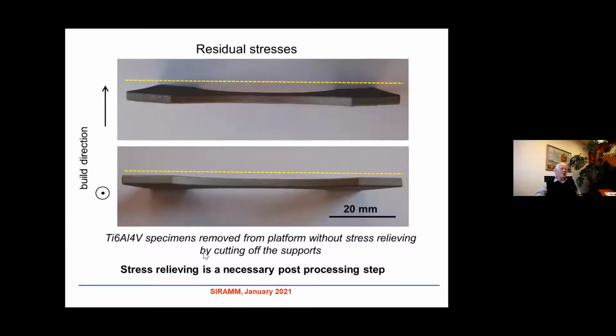Here I would like to show you specimens which we prepared for our testing of Ti6Al4V. The build direction in the first case, on the top, was in this direction, and in the second case, below, the building direction was perpendicular to the screen. The specimens were removed from the building platform, in this case without any stress relieving, simply by cutting the supports which were here, and in this case here. And what we can see is that in this case the specimen is heavily deformed, not in this case. So these residual stresses are very strong, and stress relieving is a necessary post-processing step.